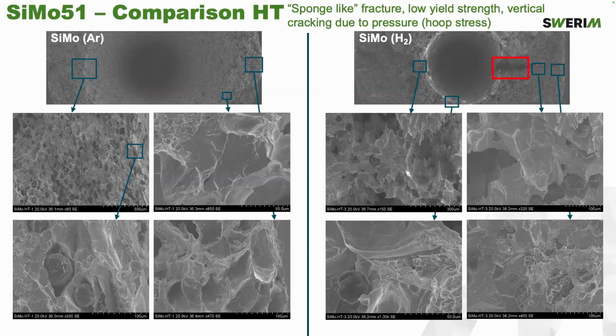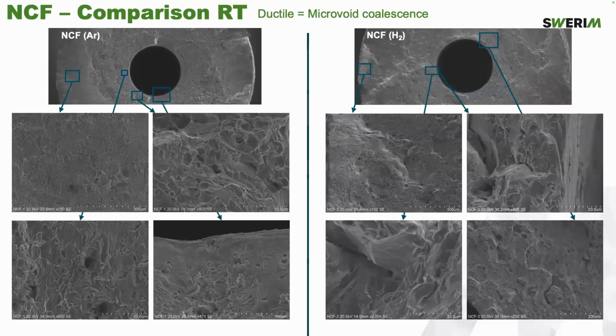But nevertheless, what is interesting is that in hydrogen gas conditions, we have also vertical cracks, which are kind of strange, but non-expected. And this is also related maybe to cracking of the material due to hoop stress, which is probably close to the strength of the material. NCF comparison, room temperature, microvoid coalescence, ductile type of failure.